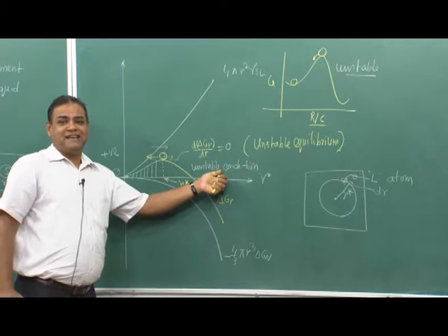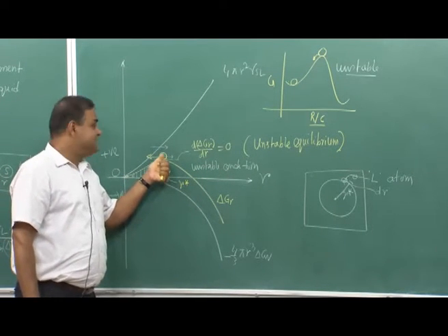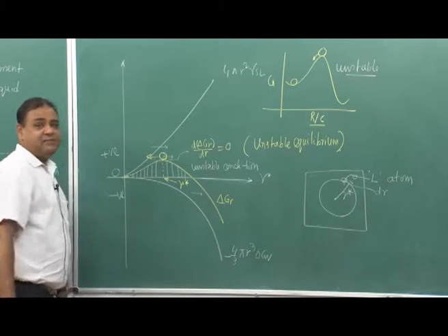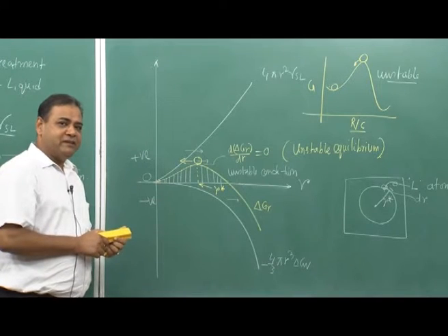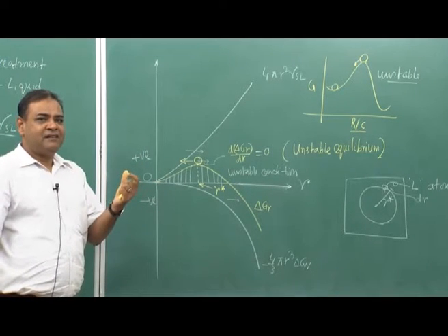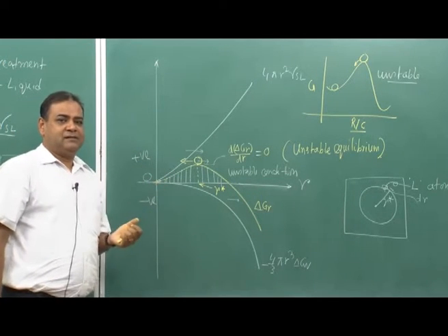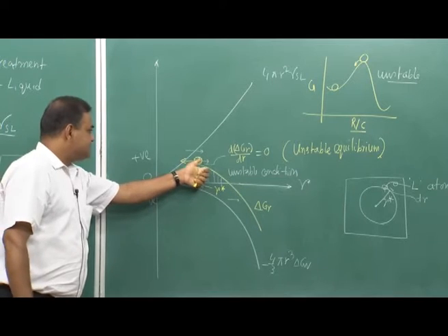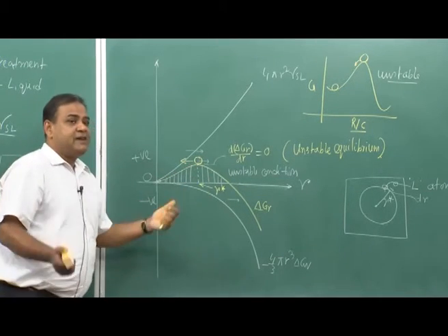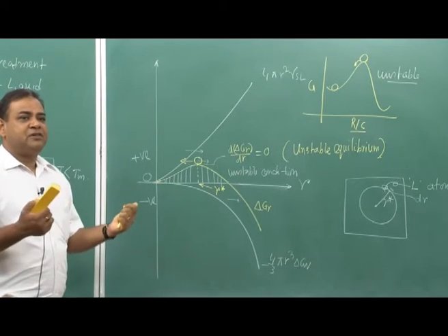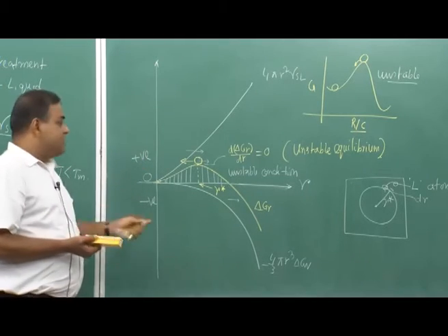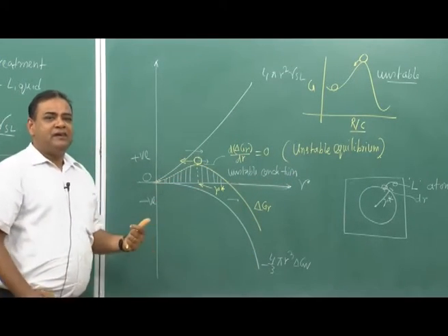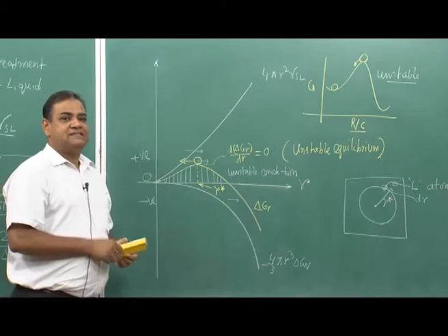and this unstable condition is always preferred, because at that time this solid can only grow its size, because it always goes to the right side. So, that means it can only increase its size. What does it mean? It means that the solid becomes a stable particle inside the liquid. The solid cannot go back and melt. So, from this to this way it melts again, and from this to this way it actually takes more liquid atoms and becomes solid, solid and solid. So, the solid grows in size. So, this instability as per this model is always good, because at that time the solid can go and increase its size. So, at that time we call it a stable nucleus.